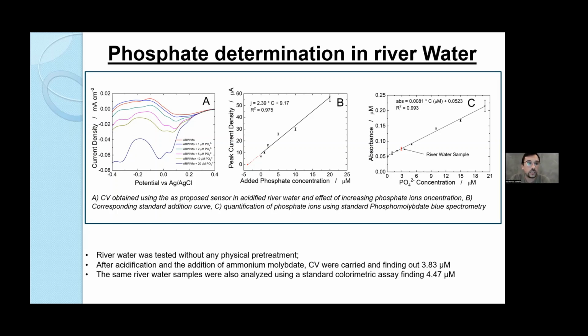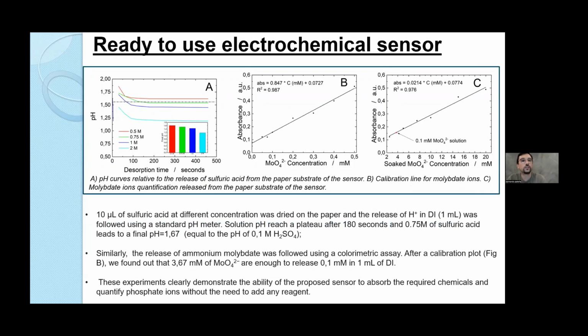But as I said, here we still added the reagents, molybdate ions and sulfuric acid, and so we cannot carry out any kind of real-time or in-situ analysis. So then we have carried out ready-to-use electrochemical sensors, and this is why we chose paper as substrate. Indeed, we have tried to see if paper could be preloaded with sulfuric acid and molybdate ions in order to be released then in the water to be analyzed, in order to make an analysis without adding any reagents.